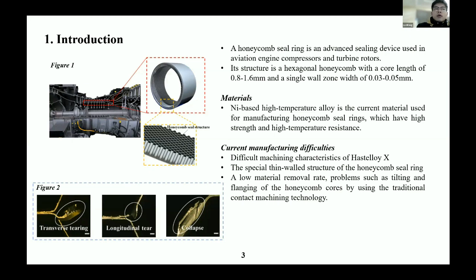0.03 to 0.05 millimeters. Due to the high temperature and high pressure working environment of the honeycomb cell structure, the manufacturing material of the honeycomb cell structure is Hastelloy X, which has high strength and high temperature resistance characteristics. Due to the structural characteristics of honeycomb cell structures and the difficult processing characteristics of Hastelloy X, the current processing methods have many processing defects, such as low processing efficiency, core cell flanging, and collapse.